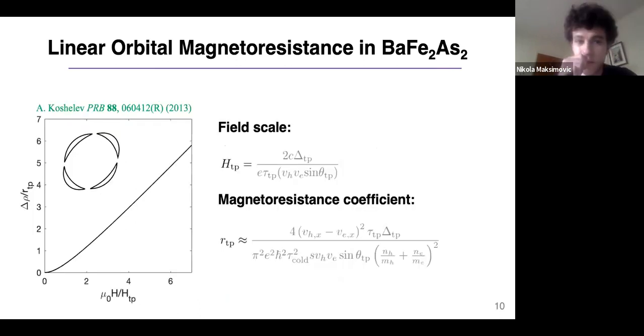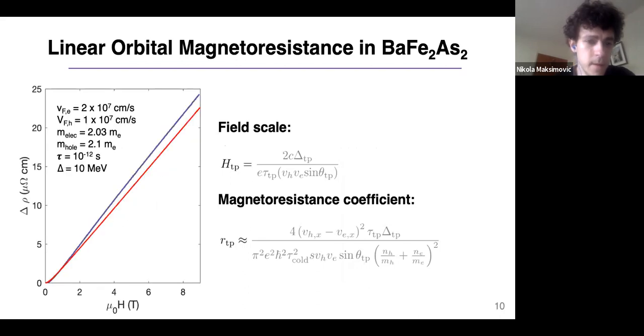So our collaborator, Alex Koshelev, did a calculation of what the magnetoresistance of this type of shape in the Fermi surface of Barium-122 will look like. There are a few magnetoresistance parameters here, and they depend in a somewhat detailed way on the fermiology and the scattering rate and things like that. What we did is we went to low temperature and used some reasonable values extracted from literature or our own experiments for the scattering rate, and we're able to model the magnetoresistance data fairly well.